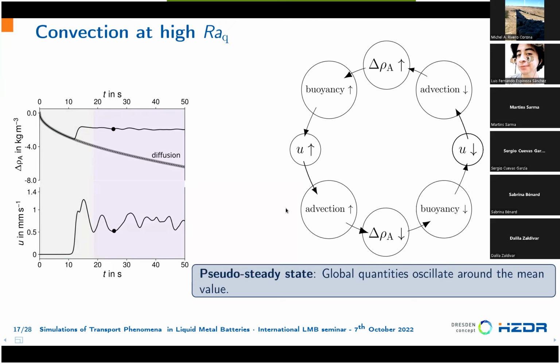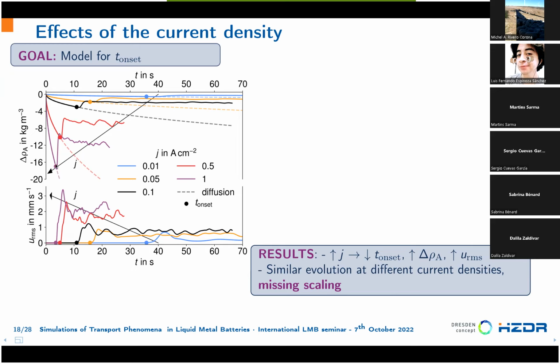So now we want to study the effect of current density on the concentration and velocity profiles. What we are doing here is increasing the current density from the blue line to the purple line. And what we see is that the onset takes place earlier. The concentration difference is larger, and also velocities are larger. In the bottom, we have the velocity. And if we look carefully at these curves, we see that there is a good resemblance across the curves. So there is some self-similar phenomenon or some similarity going on.